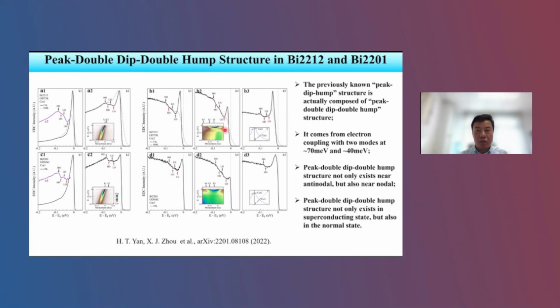Because now we know we have coexisting mode couplings, 70 millielectronvolt and 40 millielectronvolt, you produce a two-dip and two-hump structure. So the EDC is not just composed of the usual peak-dip-hump structure. It's a peak-double-dip-double-hump structure. This can be seen in Bi2212 and in Bi2201, both in the superconducting states and in normal states, even in another direction. Previously, people thought it could only be observed in Bi2212 near the antinodal region in the superconducting states. Actually, it's present everywhere: in normal states, and even in another direction.